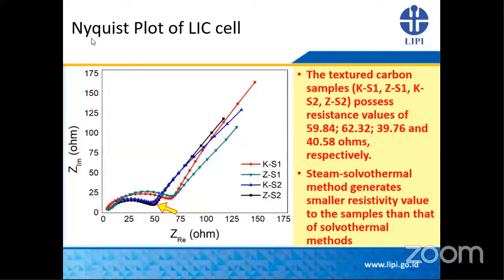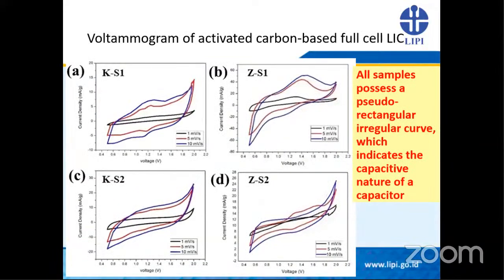So we also measured the Nyquist plot of the lithium ion capacitor cell, and we can see here that the sample with the steam solvothermal method generates a smaller resistivity compared with the solvothermal method. And this is the voltammogram of the porous carbon-based full cell LIC. We can see here the voltammogram has a pseudo-rectangular irregular curve. So this kind of shape indicates the capacitive nature of a capacitor.